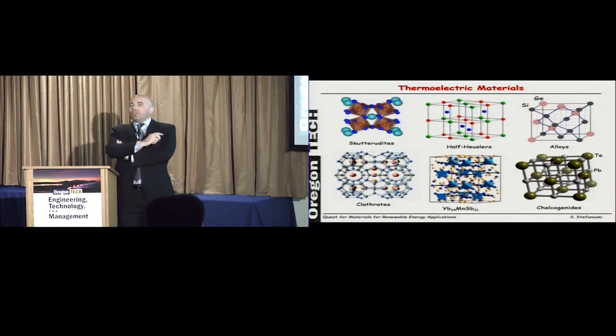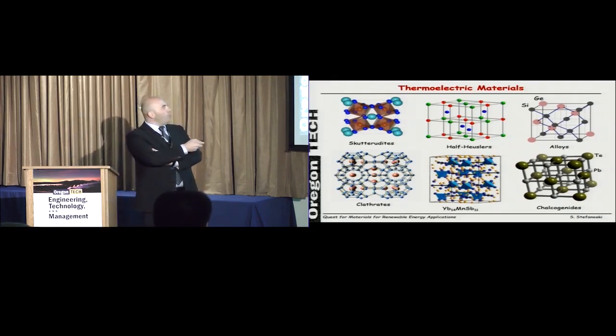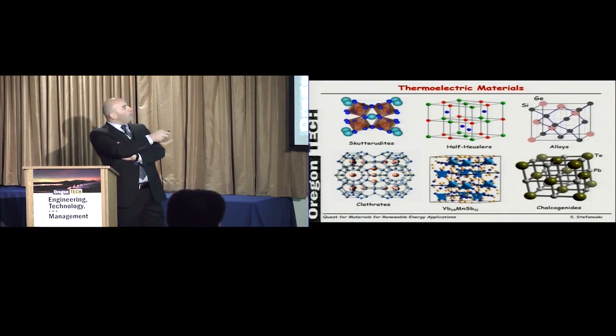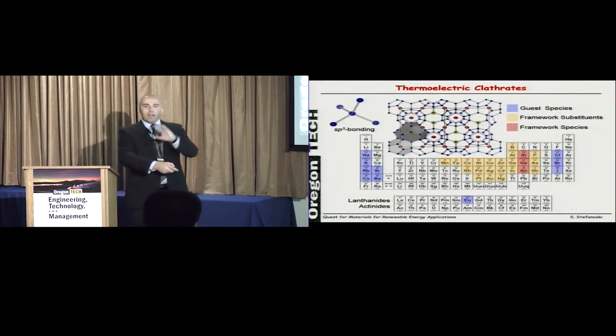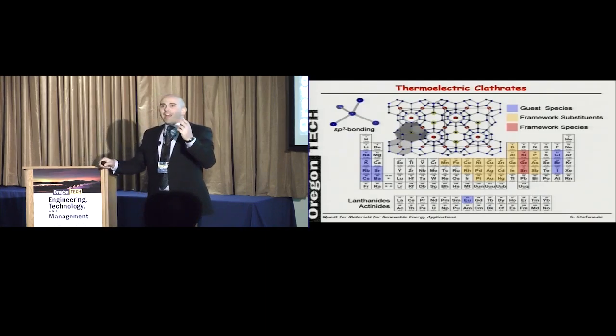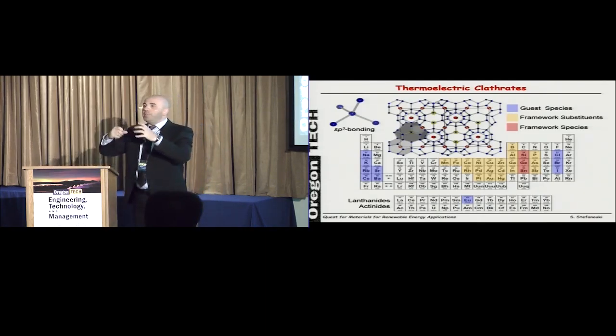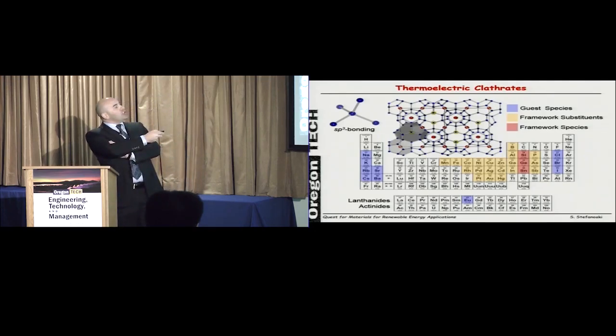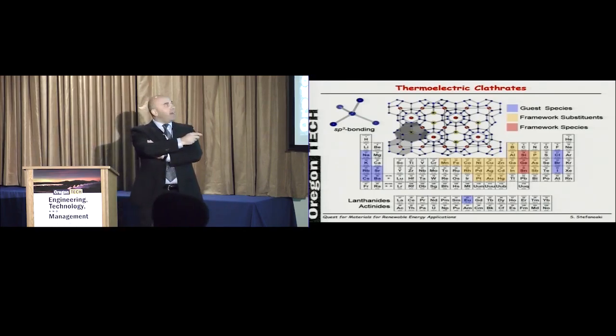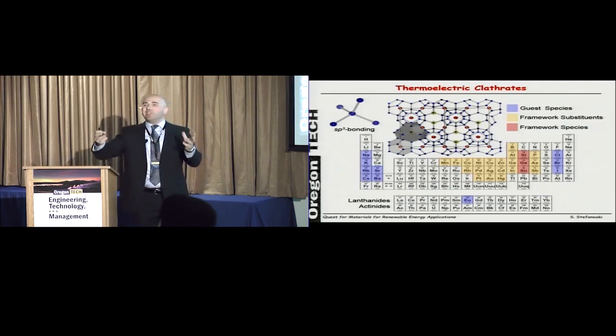There is a wide range of materials that is currently under investigation when it comes to thermoelectricity. These silicon germanium alloys, for example, are those that are employed in the RTGs. But my focus and my interest is on this particular group of materials that is called clathrates. The word clathrate comes from the Greek clathratus, which means encaged, trapped. And that would make sense if you take a look at the crystal structure of this material. You will see a three-dimensional sp3 bonded network of silicon atoms creating these cages that can trap atoms or even entire molecules inside these cavities.